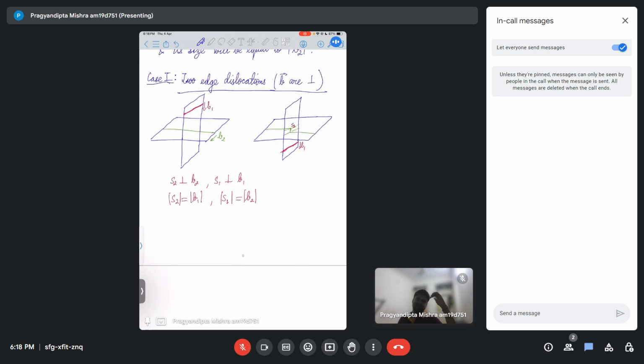Why? Because as you can see, dislocation 1 is like cutting dislocation 2 and moving it in a way that the step created in dislocation 2 has the same size that dislocation 1 has pushed it by. And how much can dislocation 1 push it by? By the Burgers vector. So that's why S2 will have the same magnitude as B1. You can see from the figure itself what the value is.